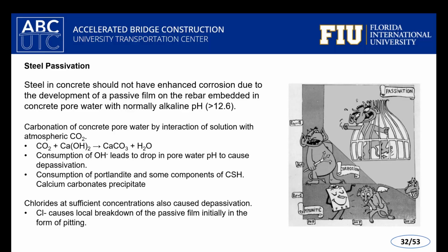So this cartoon on the right-hand side is drawn by Marcel Pourbaix. It's a famous cartoon showing some of the thermodynamics associated with how corrosion can develop for steel in various environments, including high pH concrete pore water environments. Typically in high pH environments, the corrosion devil is being locked up in a cage, and we call that passivation. So we can manage the rate of corrosion that can occur and limit that rate to where it can extend to the service life that we expect for our bridges.